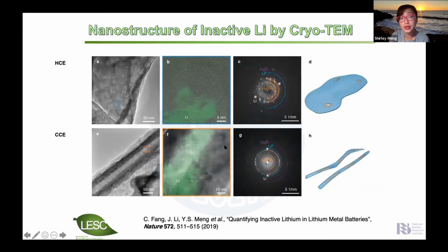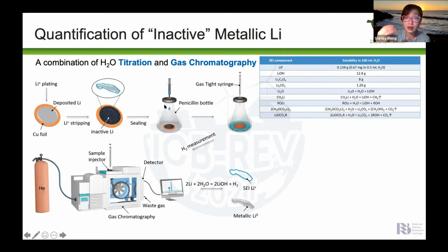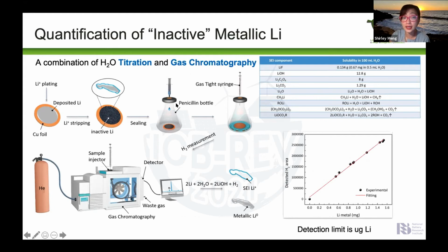And we also studied under the Cryo-TEM to confirm the hypothesis, where in the tortuous and viscous structure, you see a lot of dead lithium, and in the large granular structure, you see very few places has the lithium trapped. And to quantify accurately the total amount of lithium trapped inside the SEI, we turned to this very simple and elegant method called titration gas chromatography.